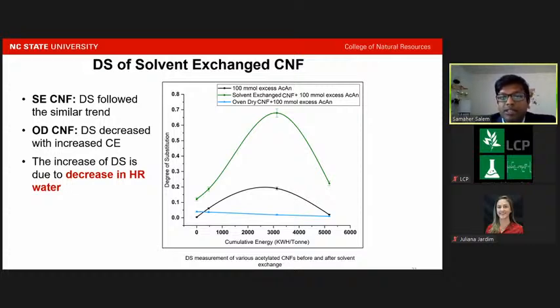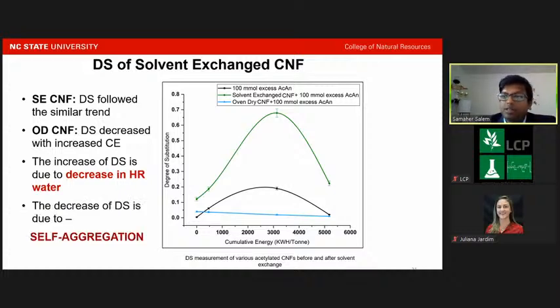But still it decreased. And the decrease in the degree of substitution was due to another factor, which is known as self-aggregation and intrinsic properties of the nanocellulose. And the oven-dry nanocellulose also shows that the degree of substitution decreases as the energy was increased. And this is due to the self-aggregation. When we dried the sample, aggregation increased with the increase of energy supply, and thus the reactivity of the nanocellulose decreased.